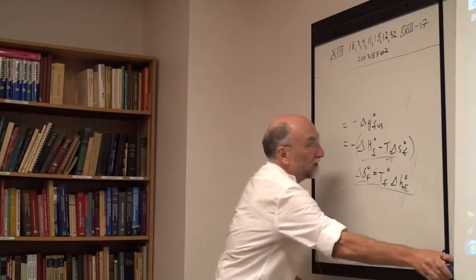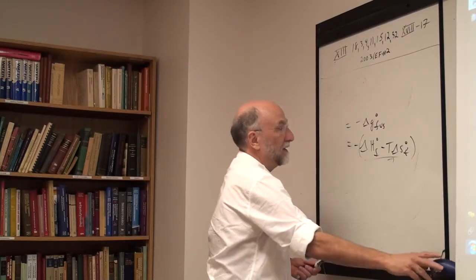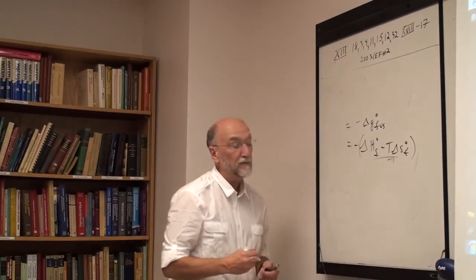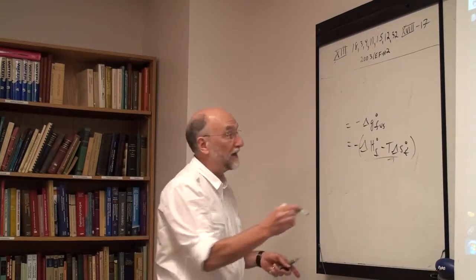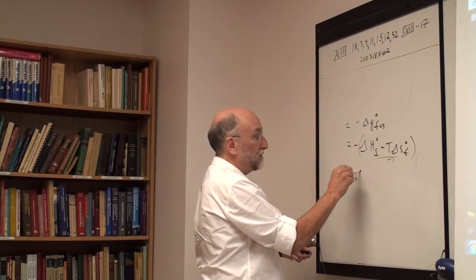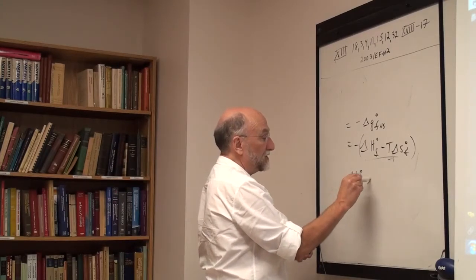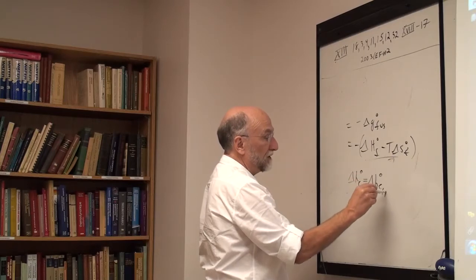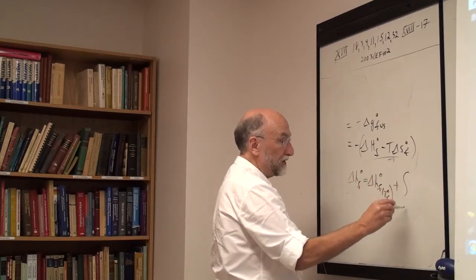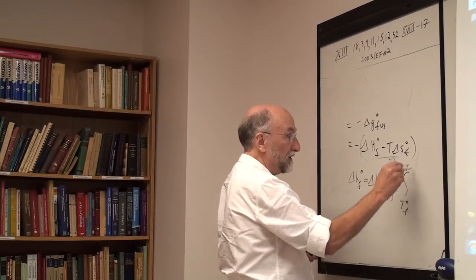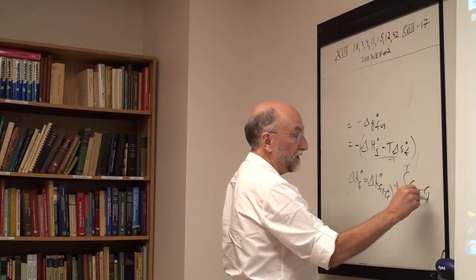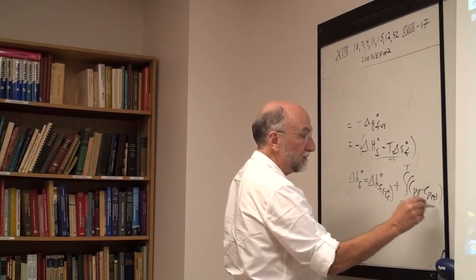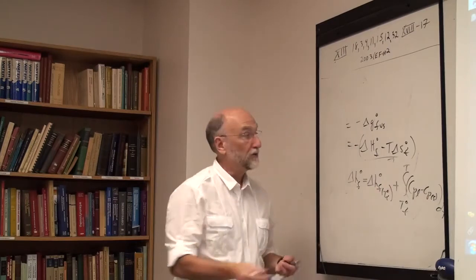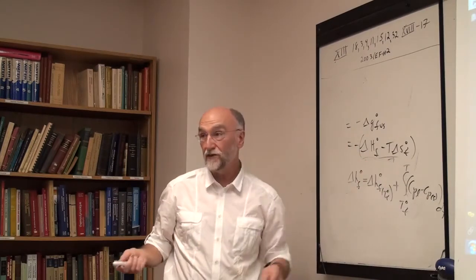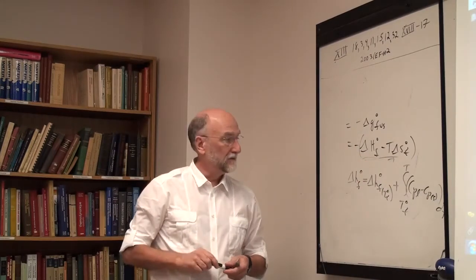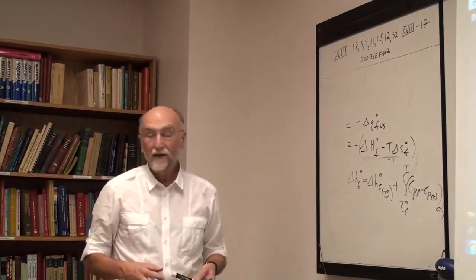If they're not independent of temperature, and they'll be independent of temperature if Cp solid equals Cp liquid. If they're not, then the heat of fusion at any temperature T was equal to the heat of fusion at the melting point plus the integral from T fusion to T of Cp liquid minus Cp solid dT. So this becomes a function of temperature, and that becomes a function of temperature. Or maybe there's a minus sign you have to think about.